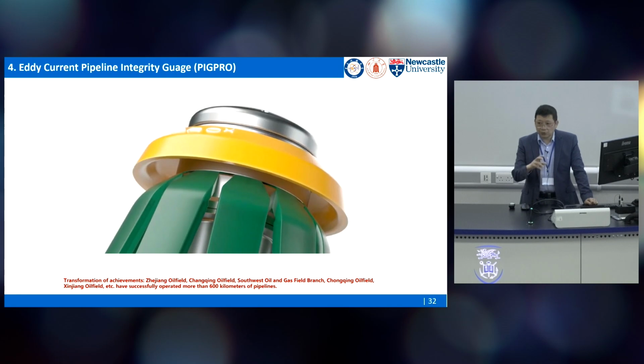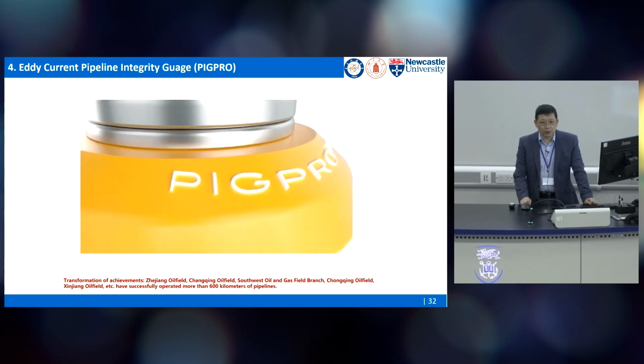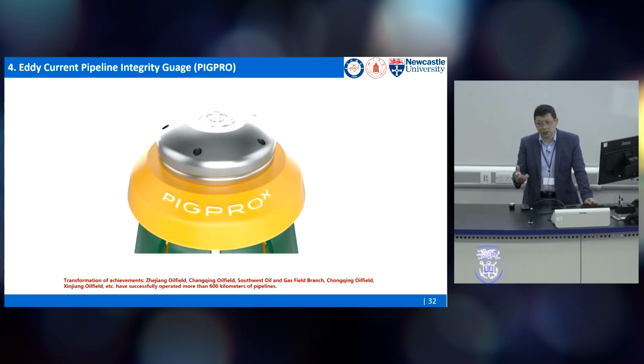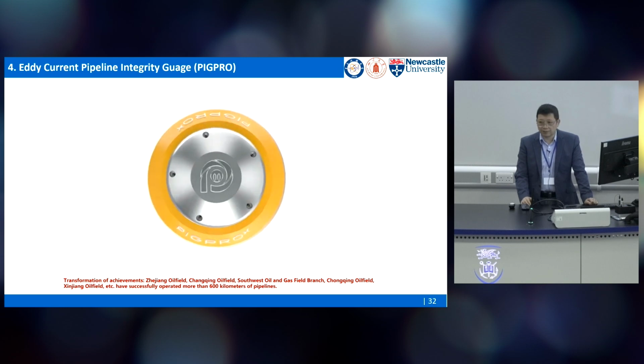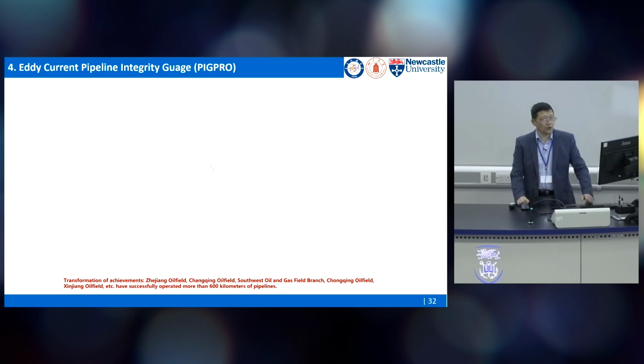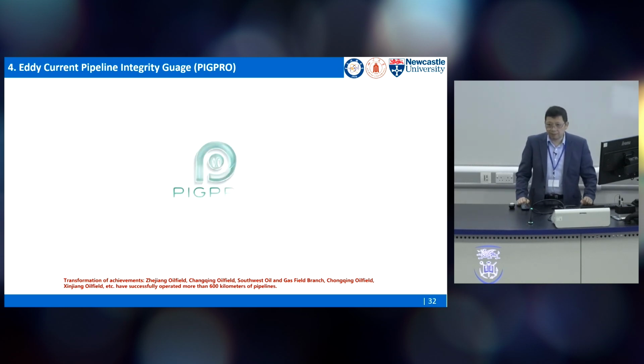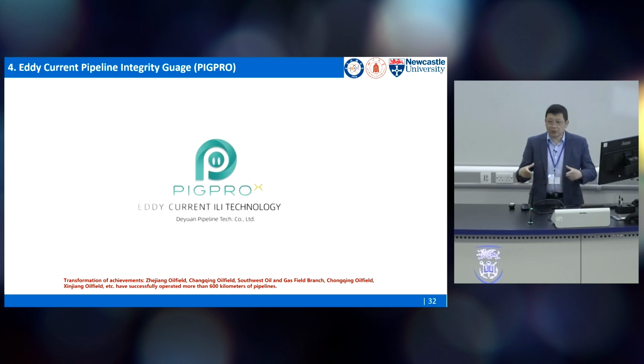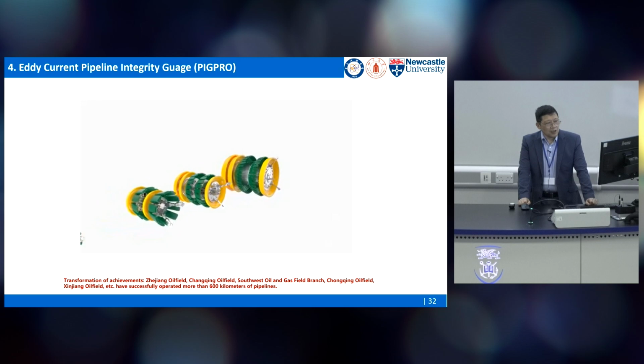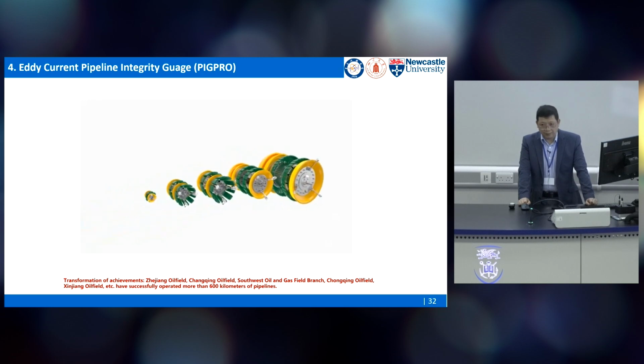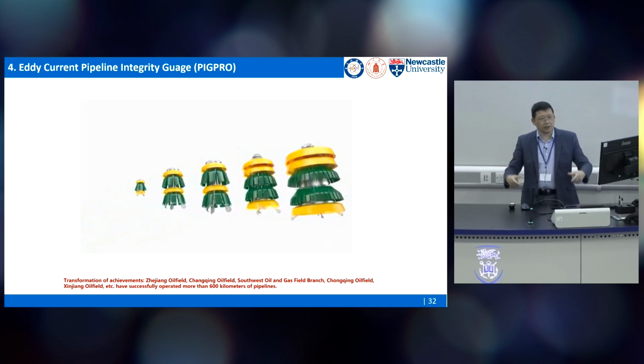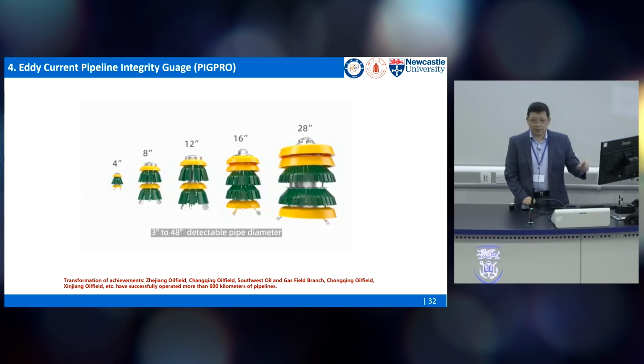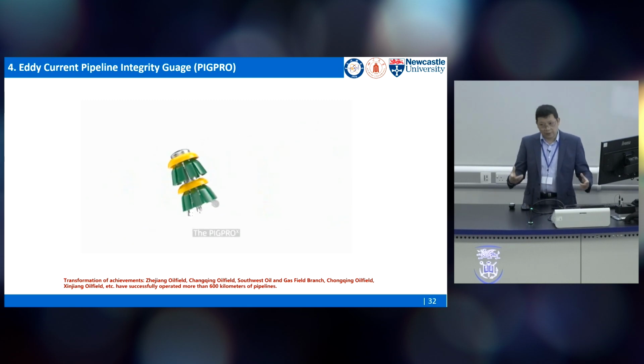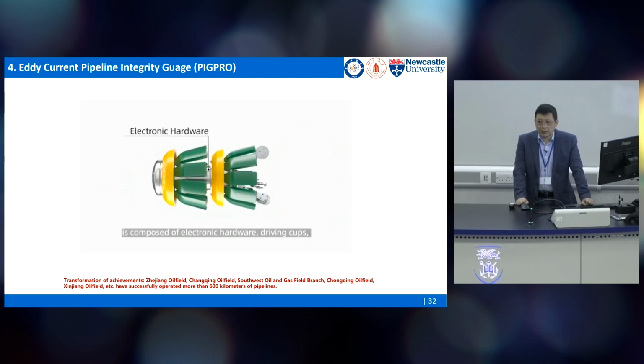And the tradition where you use this one, just use a magnetic flux leakage, which is a big system and is very big. That's okay for a long distance pipeline. But for a branch pipe, the pipeline is small, for example, less than half a meter in diameter, so it's very difficult. Then we use eddy current. We can get a very good sensitivity and a compact system.